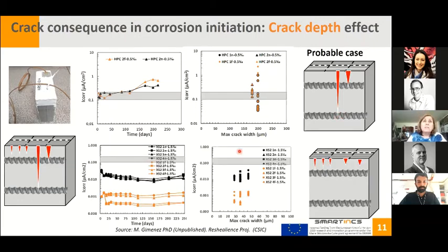When we have the ultra high performance fiber reinforced concrete, however, the situation is significantly improved, and after a similar period of time of exposure, the corrosion is far from being initiated, even in the case of the second level of reinforcement. What could be the situation here? That the cracks are very thin and are healed, and even if they reach the reinforcement, the corrosion was not possible to be initiated, or the cracks are not penetrating completely to the rebar level, and so they are healed, but the corrosion is not initiated.